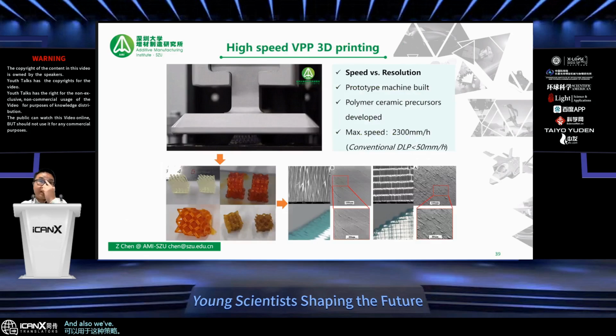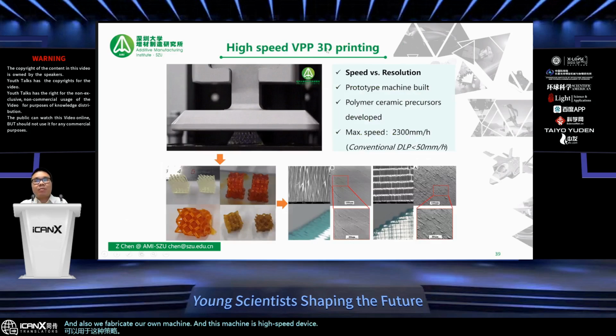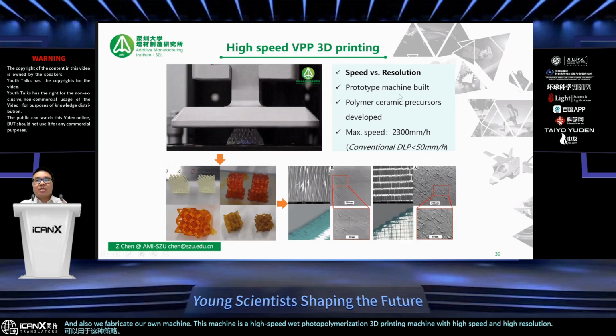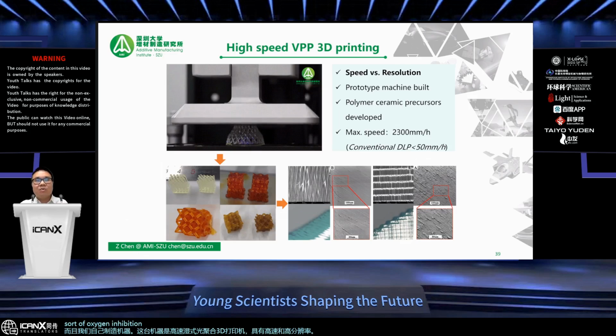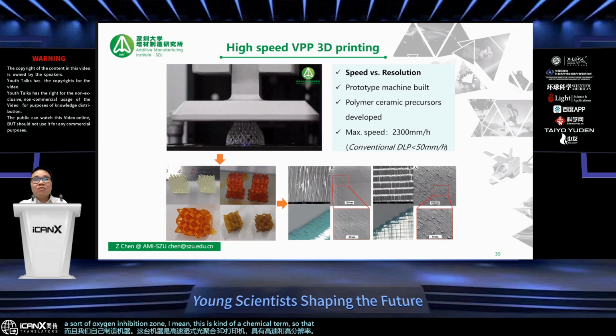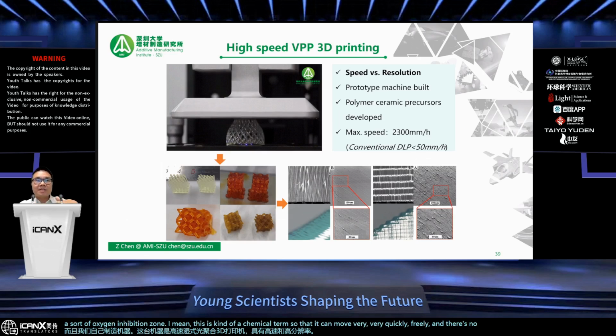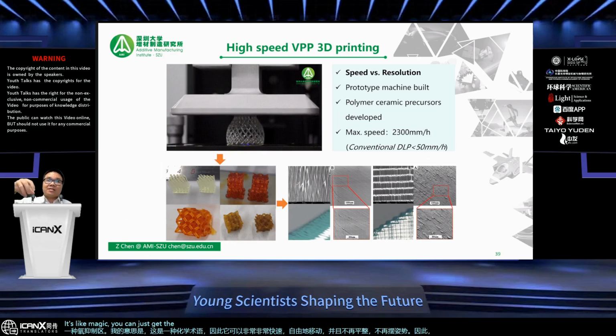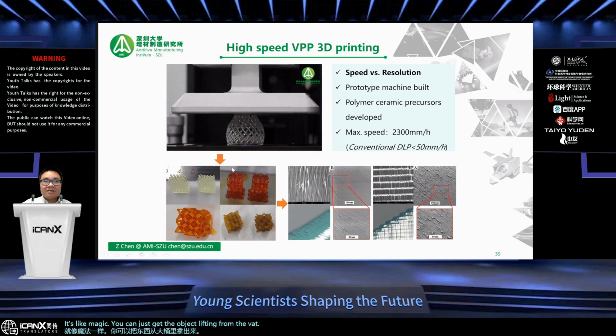And also we fabricated our own machine, a high speed vat photopolymerization 3D printing machine with high speed and high resolution. Because there's an oxygen inhibition zone, I mean, this kind of chemical term, it can move very, very quickly and freely, and there's no longer leveling, no longer posing. So it's like magic. You can just get the object lifting from the vat. And there's of course the exposure of UV light underneath.